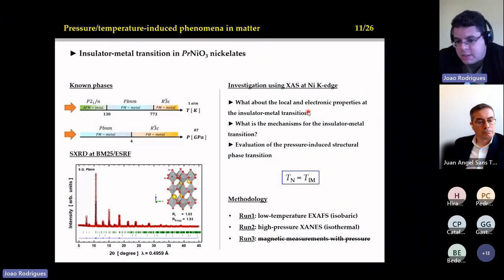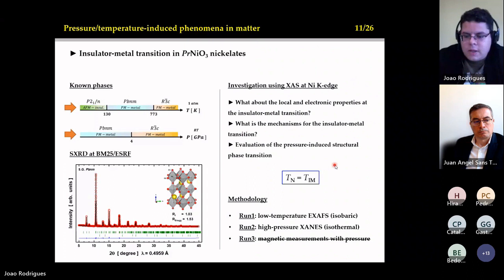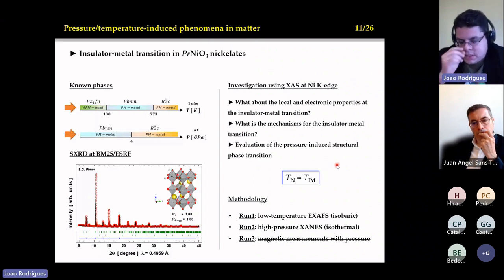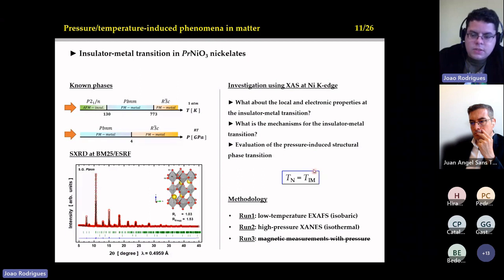And then the main mechanism behind these transitions, especially the insulator-metal transition between the insulator and the metal, from the monoclinic to orthorhombic. Okay. And this material is a very special one because the Néel temperature is exactly the same as the insulator-metal transition, which is not the case for different nickelates with different rare earths.